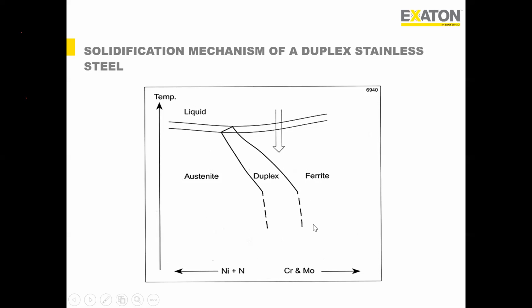But you see that a manufacturer, whether of the base material tubes or plate, or a consumable manufacturer, they actually did a lot of R&D to optimize this kind of alloy element. Although there's a range out there, we try to optimize the range in such a way that the microstructure is as perfect as possible. But during fabrication, depending on the cooling rate, it could vary. So later we'll discuss in more detail how the desired microstructure of the duplex can be controlled.